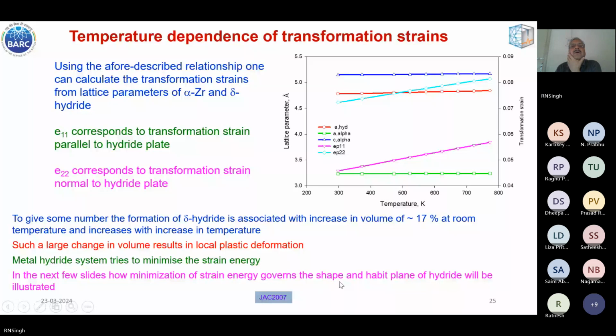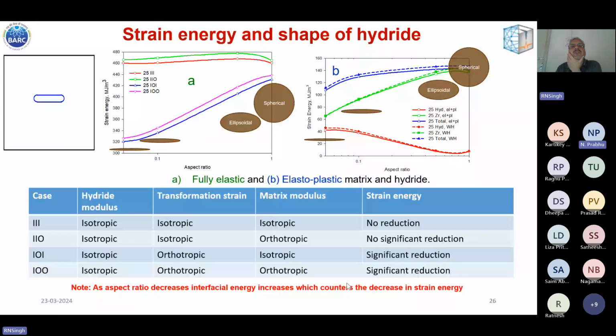Suppose we start with a spherical hydride, then the strain energy per unit volume of the hydride is very high. As you go on making it more and more oblate, this accommodation strain energy reduces. But we cannot go on making it flat like this, because once it becomes oblate, the interfacial area is increasing. So at some point there is a balance between the interfacial energy and the strain energy. Usually a 20:1 aspect ratio is observed for hydrides.